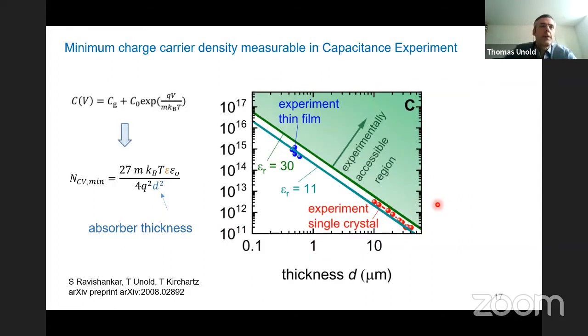Next slide. So what you can do now with a relatively simple model is say the capacitance consists of the geometric capacitance and this injection capacitance. And you do the math, you can calculate this minimum CV carrier density that you should be able to measure in a device. And you get this equation here. And there's not much in there. Actually, it's the epsilon, and it's the thickness of the absorber squared. And we have plotted that here. So this is the charge density here, and this is the thickness of the device, a double logarithmic plot.